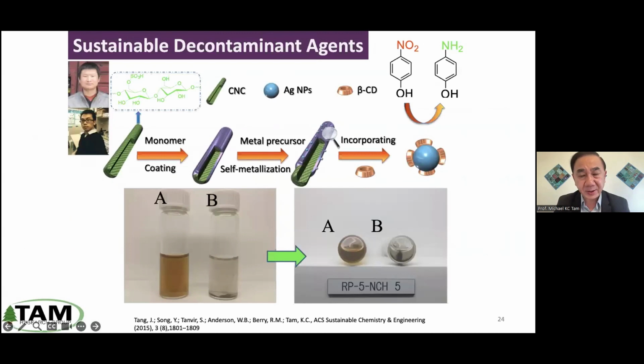The other system that we have worked on, which can be used as an antimicrobial compound and a catalyst to convert this amino compound, is to coat this nanoparticle with silver. So we basically take this nanoparticle, coat it with dopamine, and use the silver ion to form silver nanoparticles, which are quite small, between 2 to 5 nanometers.